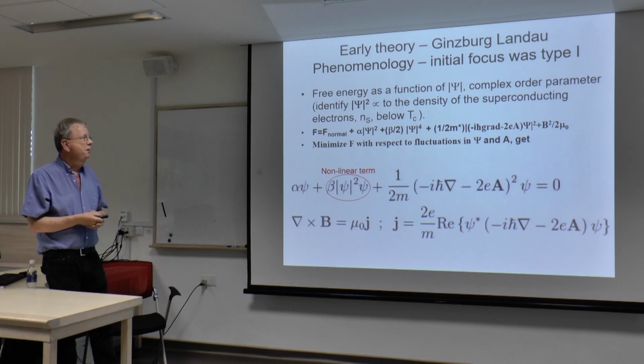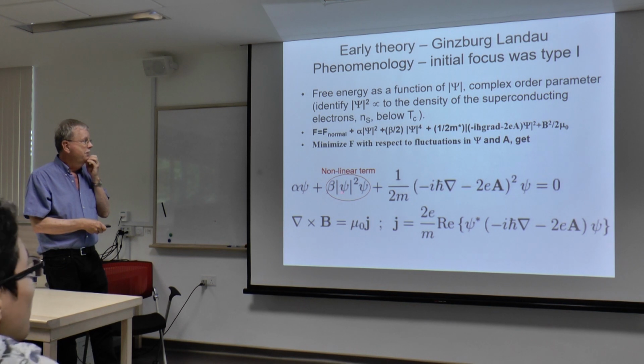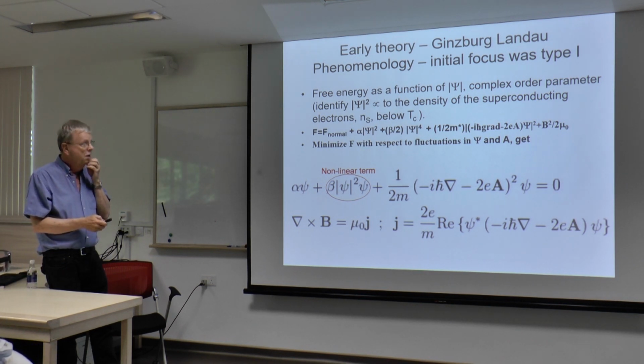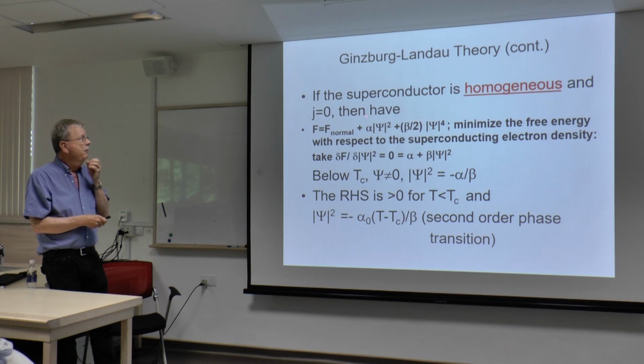Since I presume there are a lot of theorists in the audience, I briefly make a foray into theory. So we're going to have a complex order parameter, psi. The absolute magnitude of psi squared is going to be proportional to the density of the electrons, which makes it useful. And in simple Ginzburg-Landau theory, put together these terms. You minimize the free energy with respect to fluctuations, and you get this. And moving right along, here's a few caveats. Minimize the free energy with respect to the electron density, get this.